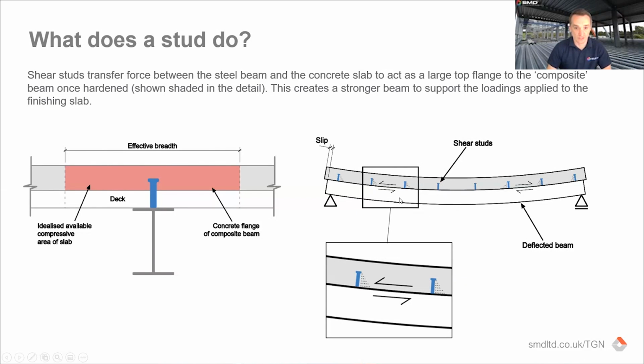So what the shear stud does to transfer that force is, when you apply the load to the slab, so here we have a slab on a beam between two supports, and as the slab goes in and beam goes into bending, you get slip at the end of the beam, and that basically puts force at the interface between the slab and the beam. So if we had no shear studs at all, that slab and that beam would be able to act independently to each other. By putting shear studs in, what you create is a resistance to that slip, and what you get from that is then the beam force in one direction, the slab force in the other, and the shear stud is what then transmits the force between the concrete and the beam.